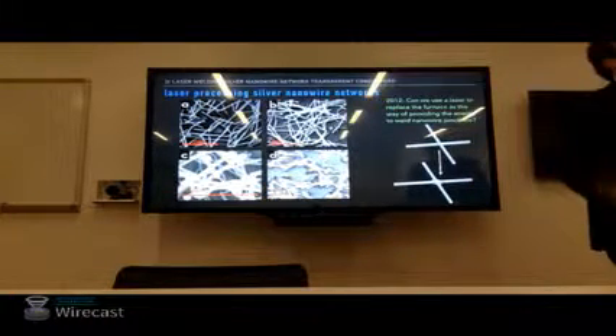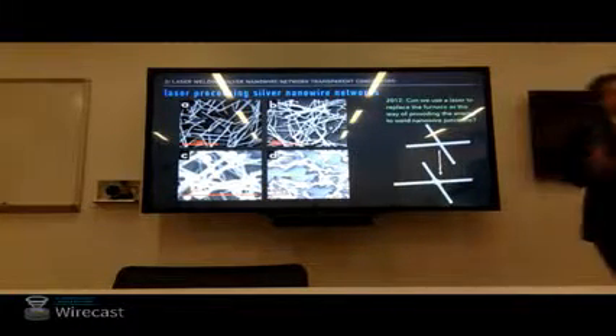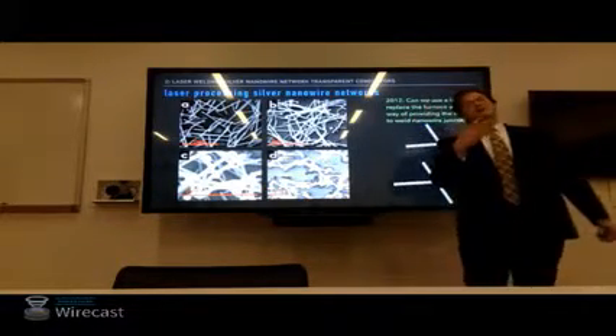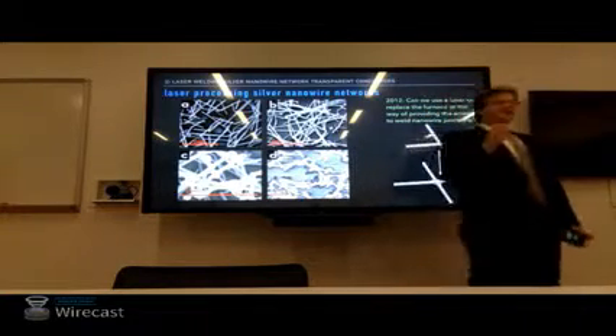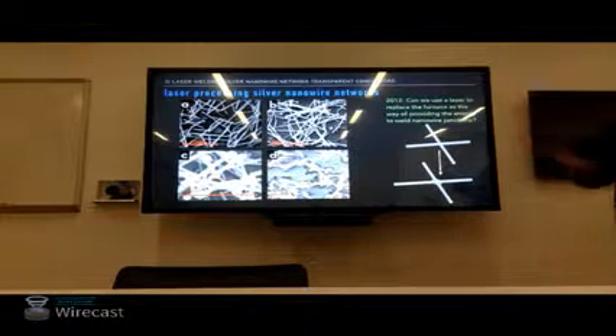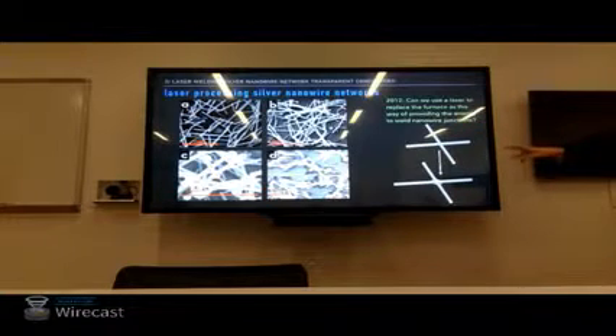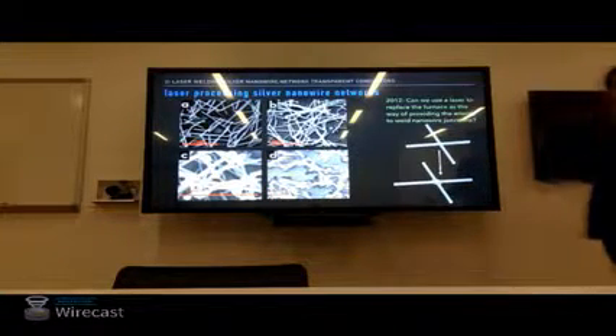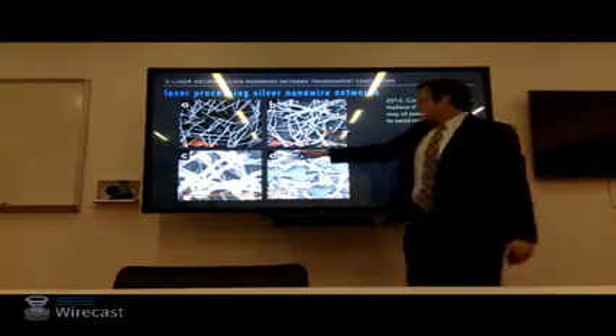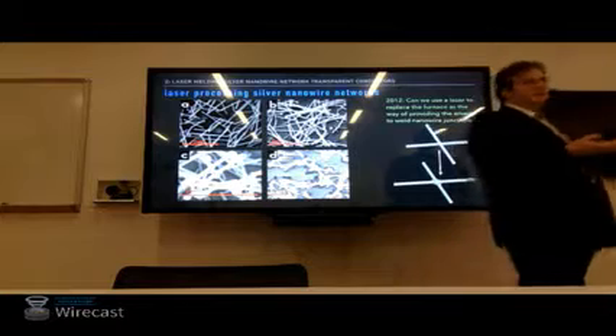We can look for direct evidence. So we can make nanowire networks and put them in an SEM, scanning electron microscope. And what we see is nanowire networks that are not laser processed, such as in A, have these well-defined sides and edges. In B and C, we start adding the laser, with B having a lower energy density than C. And we start to see signs of interaction of the light with the silver cylinders. And we see evidence that nanowires have fused together. We also see at the ends of nanowires the silver balling up.